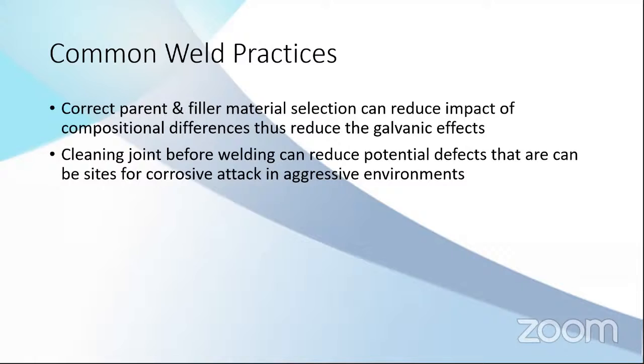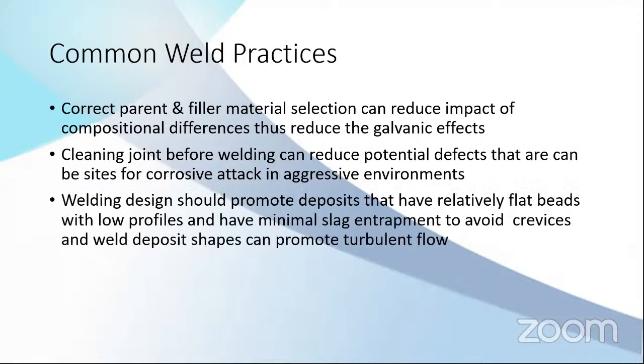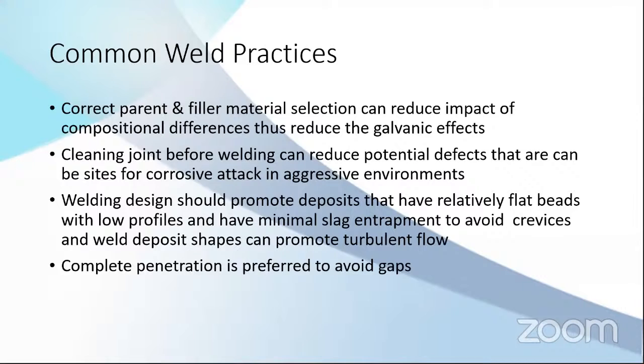And fully clean all the joints, especially for corrosion resistant material. If you have moisture left or residual oil on the joint, it will impact the corrosion resistance a lot. If possible, the design should have flat beads and a low profile, to avoid crevices and stress concentration, especially when related to stress corrosion cracking. Complete penetration is preferred for corrosion resistant material, because if there is a space in between, that area can be the start of corrosion.